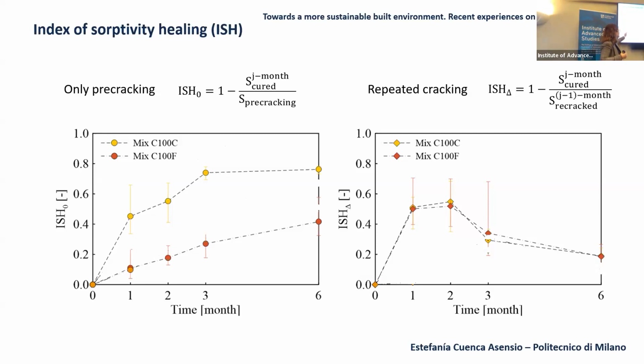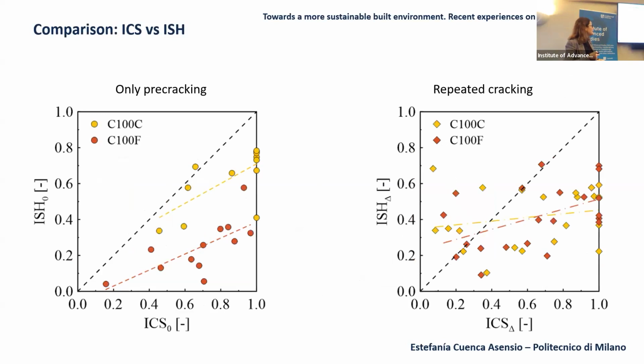The tendency is like this over a long time. It's better also in this case for the healing without the fines. This is due to the granulometry, the size of the fines, so it absorbs more water. So in terms of healing, this behavior was expected. But what happens regarding repeated healing? As you can see here, after 1-2 months the behavior regarding the index is more or less constant. But then after 6 months it drops, so it's not so good over time when we repeat cracking again and again.